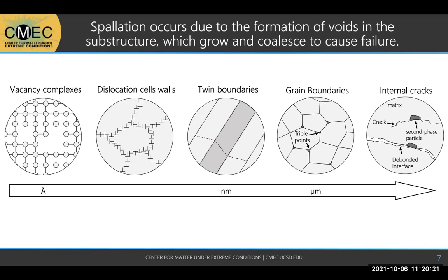At the atomic level, at the lattice level, you can have just vacancies or these lattice level imperfections, which are maybe not so important in these failure mechanisms because larger scale effects are more dominant, but it's still important to mention. The more important imperfections here are the ones at the nanometer or the micron scale. So we've got twin and grain boundaries. And so these are a lot more dominant in failure because a boundary has weaker bonding than the rest of the matrix, and it has higher interfacial energy. And so it becomes a more preferential site for void or crack nucleation.